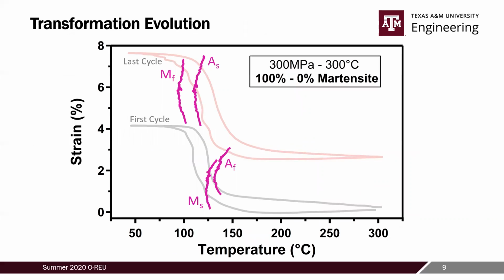Once the code was up and running, I was able to put some real fatigue data in and see what the transformation temperatures looked like. Here, you can see the evolution of the austenite start and finish transformation temperatures, and those are the temperatures where the material starts and ends the transformation to the austenite phase during the heating part of a thermal cycle. And you can also see the martensite start and finish temperatures, which are the temperatures at the beginning and end of the transformation to the martensite phase. So that's during the cooling part of a thermal cycle. So all these transformation temperatures change over time, as you can see in this plot, and some of them change a bit more dramatically than others.